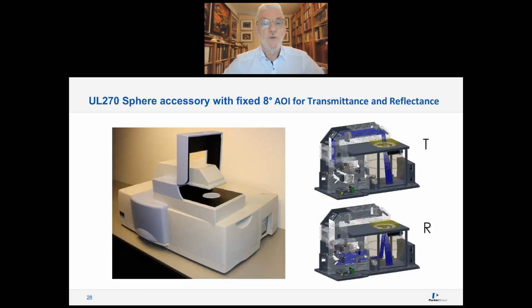The solution we got is we developed a new type of accessory. We needed a larger sphere for that, a 270 millimeter sphere, which is about the largest you can practically make and also handle with an instrument like this. With larger spheres, you don't have enough signal. This is basically the maximum you can get. And we made it in a way that you can do transmittance and reflectance measurements in a slightly different way.